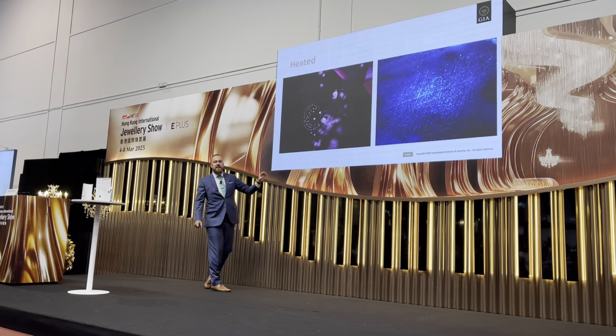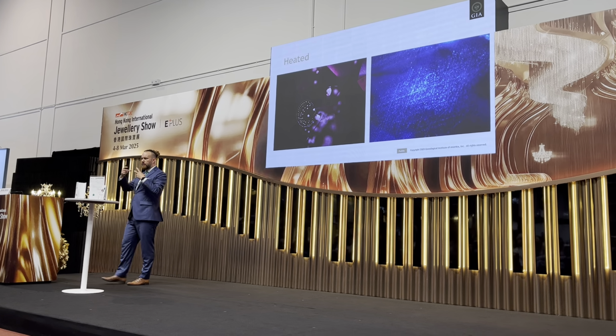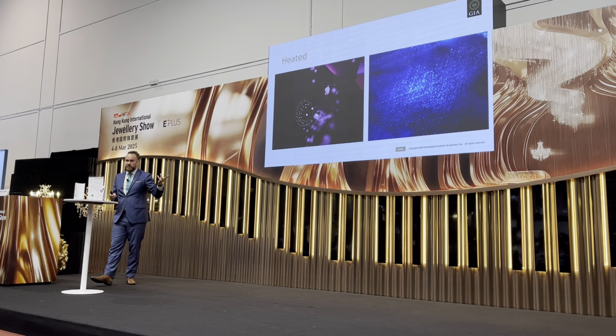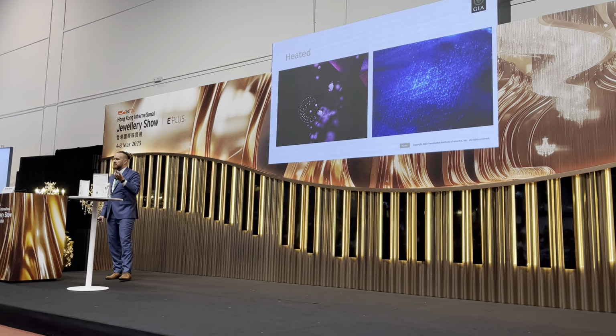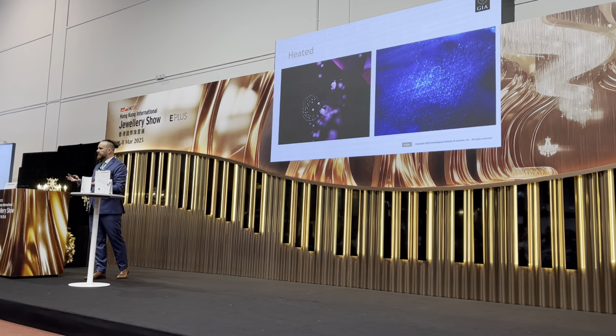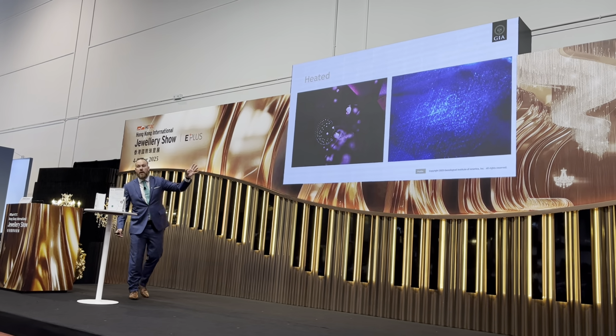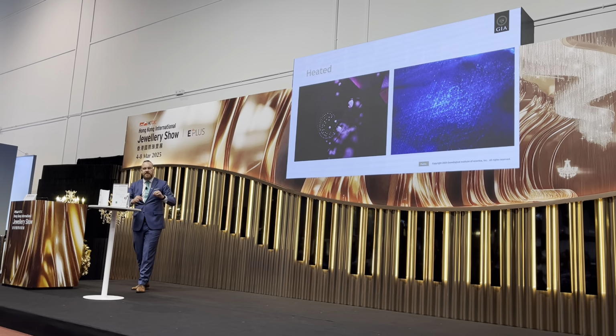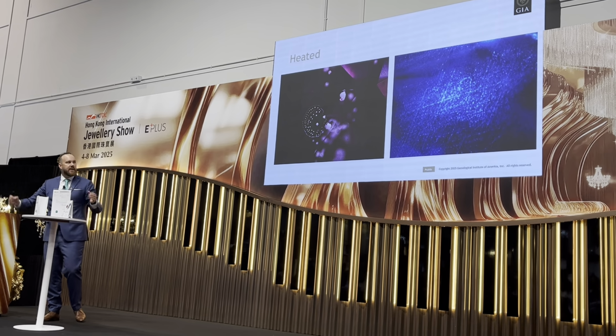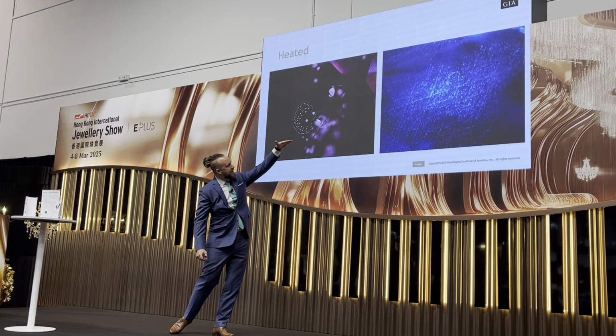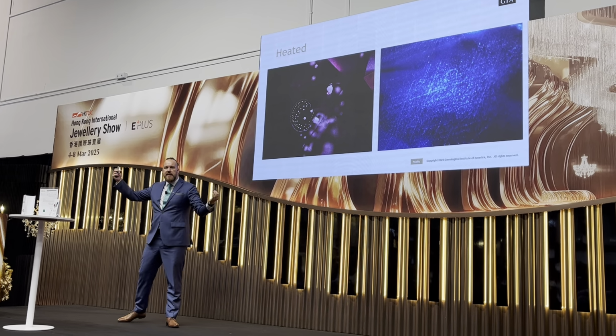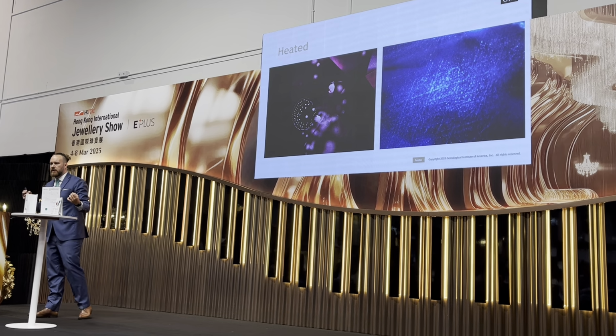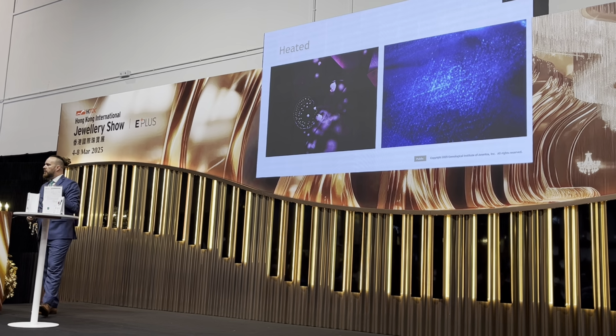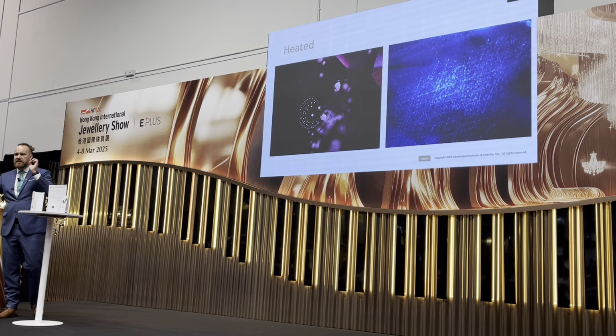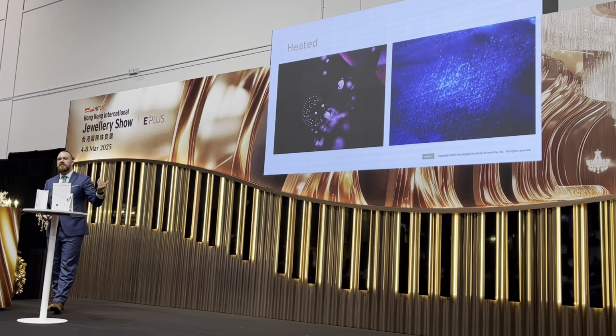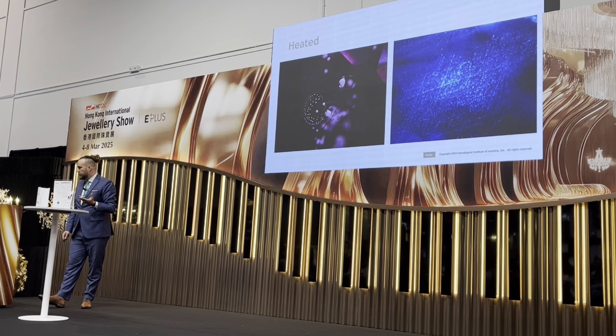The inclusions here on the left, we can see they are no longer transparent. They are completely turned frosty, and they are what we call now a snowball inclusion, because they look like these little fluffy white clouds, completely degraded by that high heat that they have been subjected to. The one on the right, if you squint your eyes a little bit, you can see that there's still the resemblance of needles in there. We can still see those patterns like this and like this and like this in there. But those long needles that used to be beautiful strands of what we call silk are now completely broken up. They are what we call peppered. So they're completely broken up in these little pieces, completely degraded. Very classic sign of a ruby or a sapphire that has been heat treated at high temperatures.